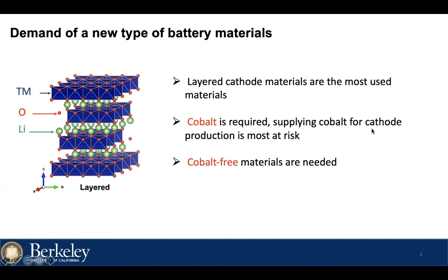Well, it turns out that cobalt is so critical for these layered materials to stabilize the structure. With larger and increasing demand of the lithium-ion battery in portable devices and electric cars, research has shown that the cobalt supply can barely satisfy this demand in the coming few years. Although cobalt is substituted by nickel and manganese in NCMs, the nickel is also expensive. So more earth-abundant elements are needed to substitute cobalt and make cobalt-free and even nickel-free cathode materials.